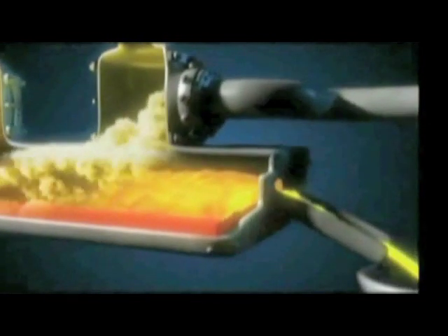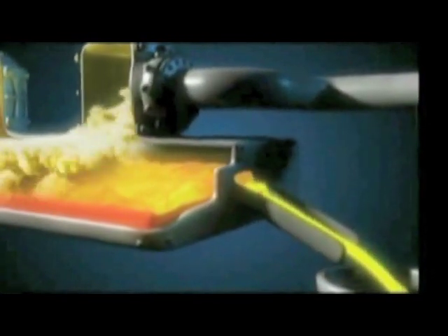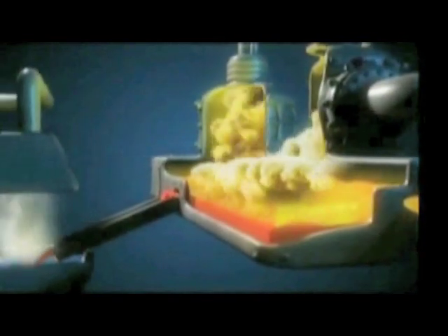A guide explains. And into a flash smelting furnace, where oxygen and temperatures over 2,400 degrees separate it into three products. Gases, which contain sulfur, slag, which is mostly silica and iron, and copper combined with sulfur, called matte, which is 70% copper. The matte is flash cooled in water, turning it into granules that are then stockpiled in an